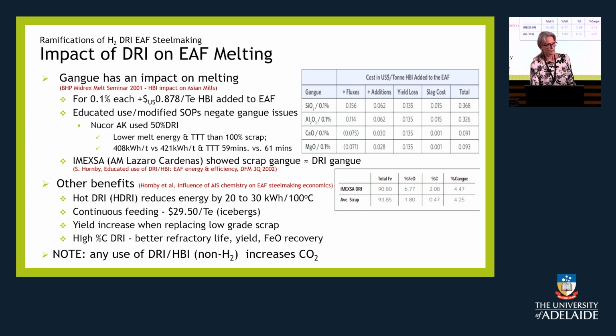Now, Nucor had shown back when 50% use of DRI actually could reduce some of the kilowatt hours and the tap-to-tap time better than the 100% scrap that they were running. Part of this is due to the fact that they had to look at their standard operating practices and improve them significantly. So in most places you won't see this kind of improvement, but they actually showed a lower meltdown energy, and they showed a drop from 421 to 408 kilowatts, and they saw a drop of 61 to 59 minutes in tap time.